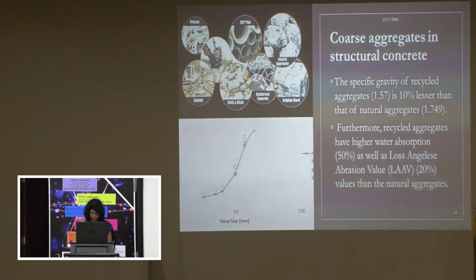Gradation of aggregates affects concrete properties such as bulk density, physical stability, permeability, etc. Hence, it is considered an important parameter. It could be seen that both natural aggregates as well as recycled aggregates have a dense yet similar gradation. Usually, recycled aggregates have higher water absorption as well as Los Angeles abrasion value than natural aggregates due to the attached mortar on recycled aggregate surfaces.